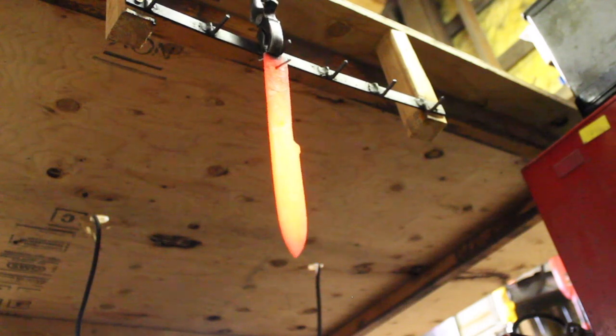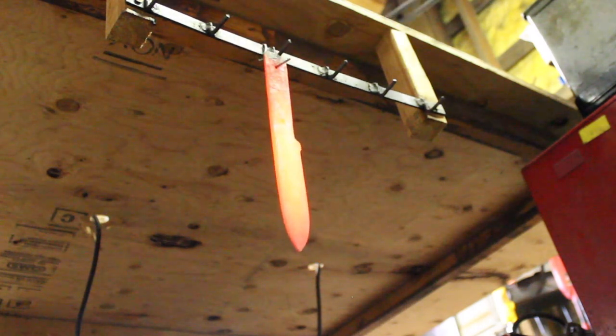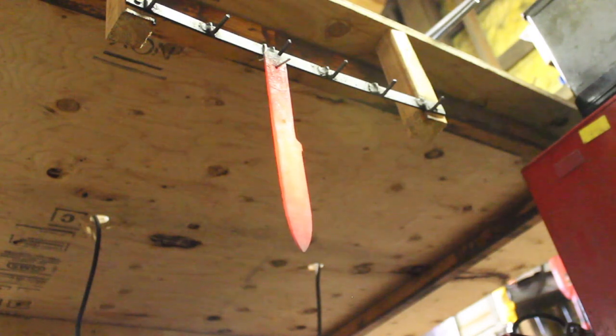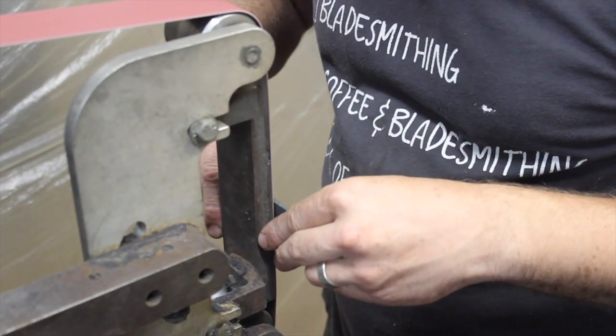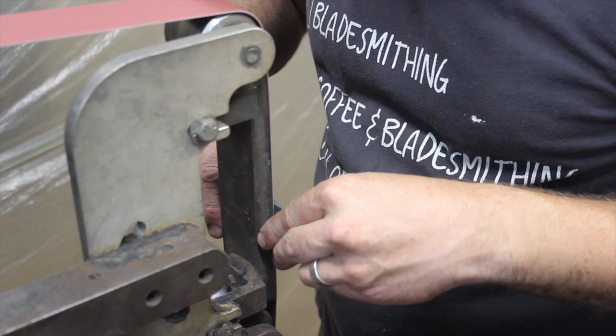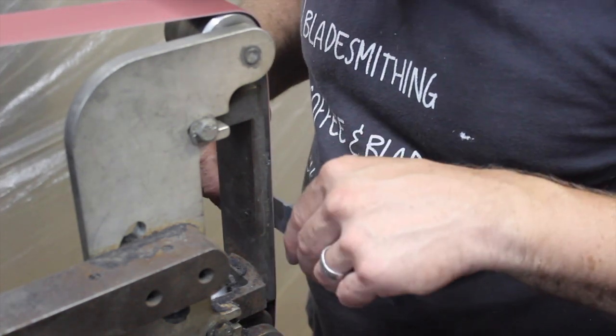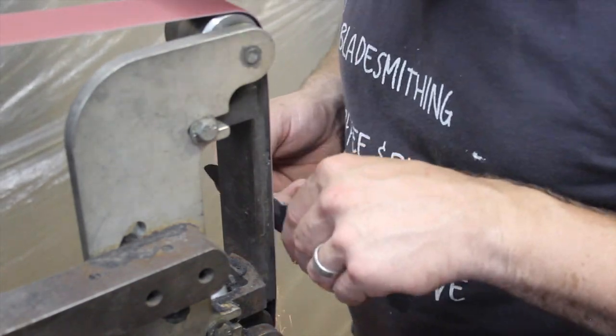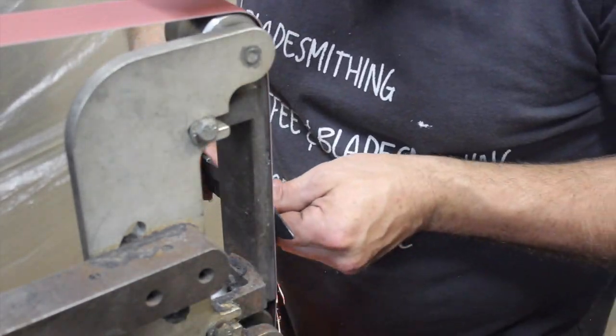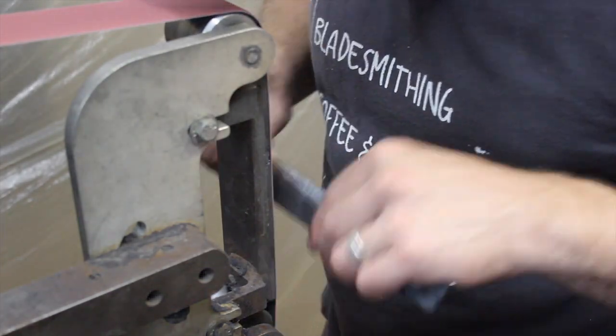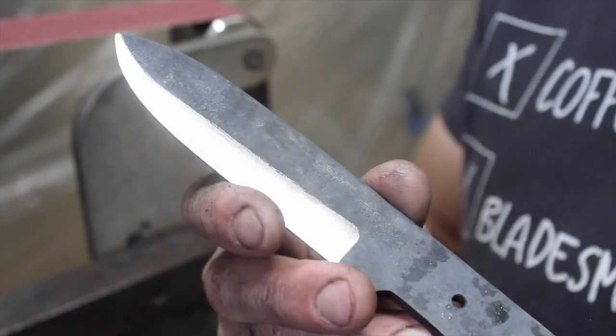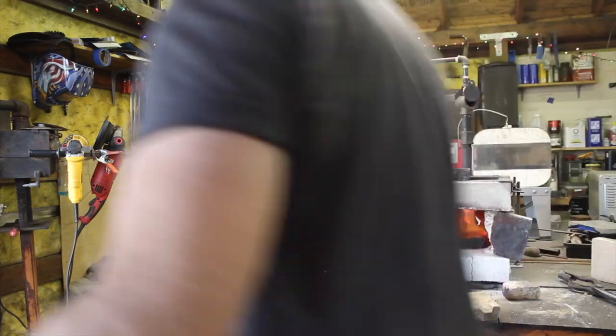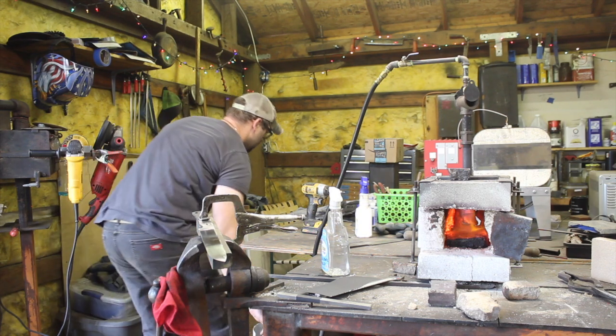So this is our normalizing cycle, and I do a total of 3 thermocycles. The following 3 cycles are for grain refinement, and the normalizing cycle particularly is crucial. It relieves a lot of the stress created by forging and puts everything back where it needs to be. Those processes are a very important part of making a quality blade, particularly when you're forging a blade. So I'm just doing a rough grind here, and that brings a uniform edge thickness that's still much thicker than the finished edge, but preps it for quenching.